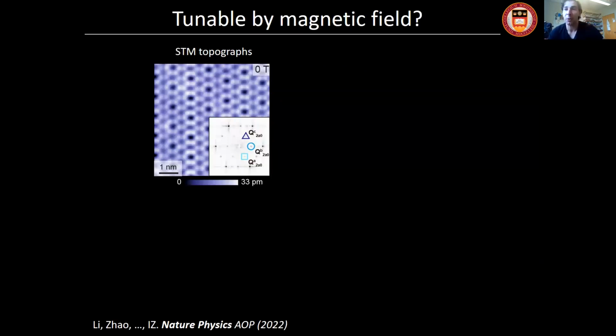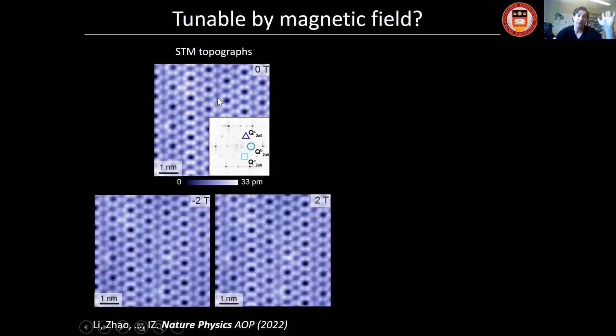So the last piece of information we wanted to pursue is, does it exhibit magnetic field dependence? There have been proposals of different orbital loop currents that can generate this charge density wave state that could potentially couple to the magnetic field. The way to investigate that, we took basically the same data sets over and over again in different fields. So this is the topograph at 0 Tesla, 2 Tesla, -2 Tesla. We apply magnetic field perpendicular to the sample surface. We don't yet have the capability to apply in-plane magnetic field, but plus 2 Tesla is out of plane, parallel to the C-axis, and -2 Tesla is anti-parallel to the C-axis. And you can see by eye, these look virtually indistinguishable. This is the same region of the sample.